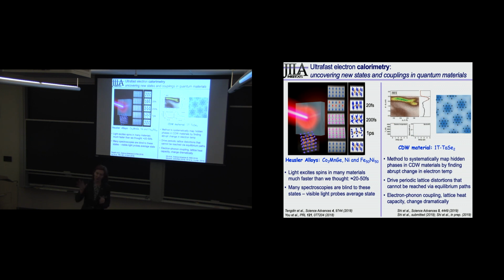What we found by falling over it in the lab is that if your material undergoes a phase transition while the electrons are cooling, because the coupling changes, you should see that phase transition written into the electron temperature. So that's why we call it ultrafast electron calorimetry: we get access to the electron heat capacity separate from the lattice heat capacity, because they're decoupled for a picosecond, which is on the order of the time it takes for very hot electrons to undergo enough electron-phonon collisions that you can actually cool the electrons. It turns out we've been looking at a few different materials using this approach, magnetic materials and charge density wave materials. And in both cases, we were able to find some curious new behavior.